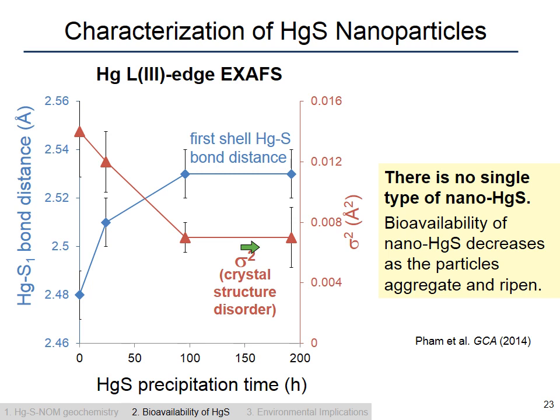So this change in structural disorder is also correlating with the methylation potential of mercury that we observed. So the take-home here is that there's no single type of nanoscale mercury sulfide, and it doesn't have a single bioavailability because it depends on the crystal structure, the aging state, and the degree of aggregation. And as nanoscale mercury sulfides age with time, they'll tend to aggregate and also ripen. Their crystal structures will ripen, and that influences their bioavailability.